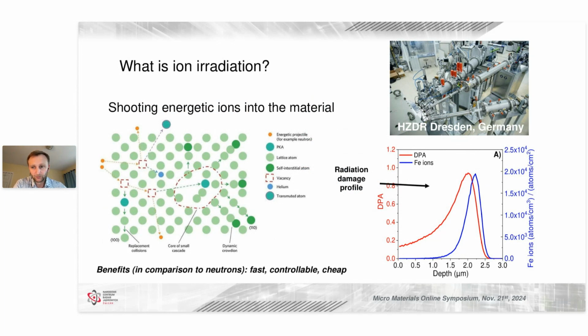There is one pitfall of this technique. The radiation damage profile is quite narrow. Usually, we manage to change the volume of the material to a depth that does not exceed a few microns. Therefore, we are creating what is called a thin layer inside of the material, and we need techniques which allow us to probe both mechanical and structural properties only from this irradiated layer, and this is where nanoindentation comes in quite handy.